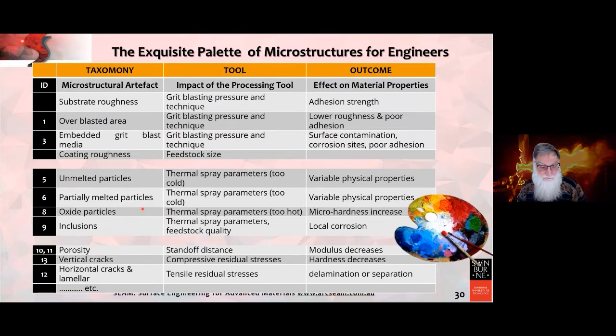So what I've done quite a few years back actually was look at the microstructural artifact, look at the tool, and look at the outcome. So I'm not going to go through all of these, but let's look at number 5. For an unmelted particle, thermal spray parameters, probably too cold, and you get variable physical properties. For porosity, and these numbers are all keyed to the microstructural features shown in the previous slides, for porosity, standoff distance, and it changes the modulus of the material. So what we have now is a way of getting to an outcome. So we can now control the outcome by choosing the tool, by understanding the microstructure, the beautiful microstructure.